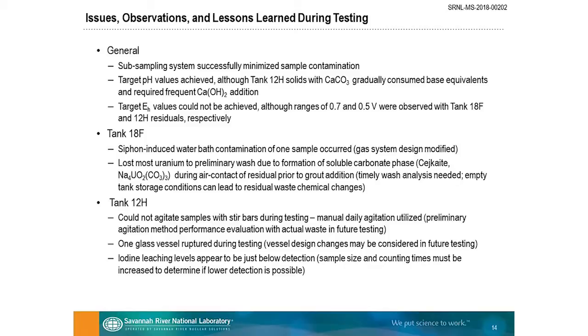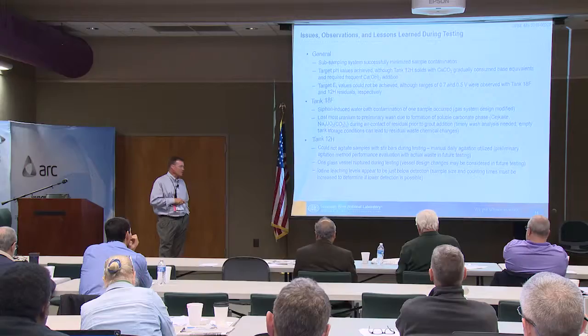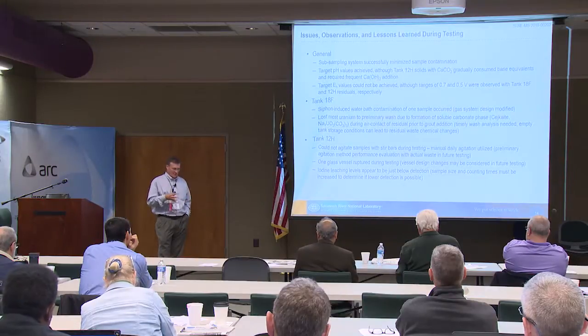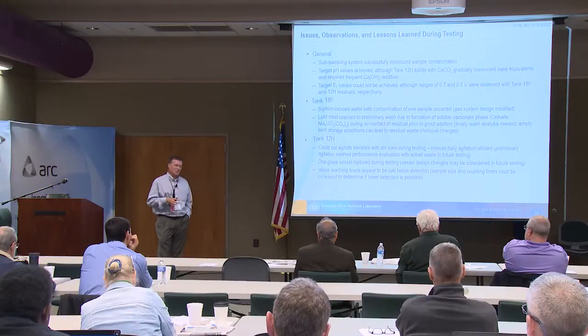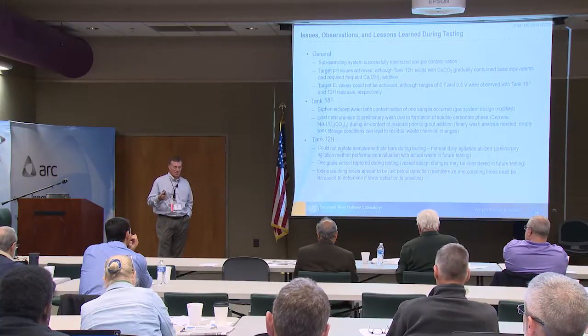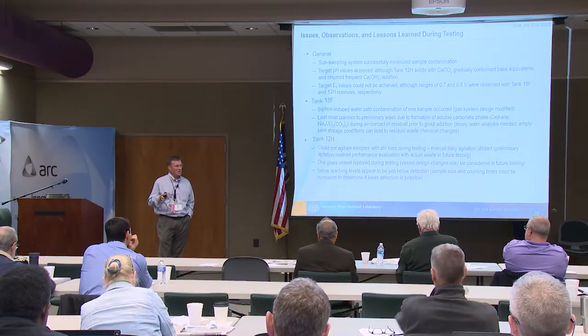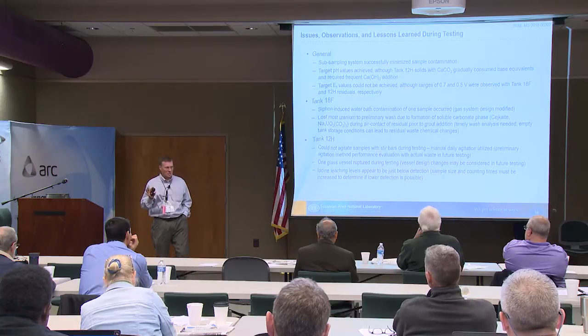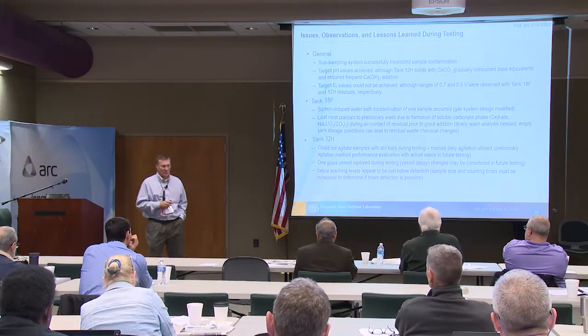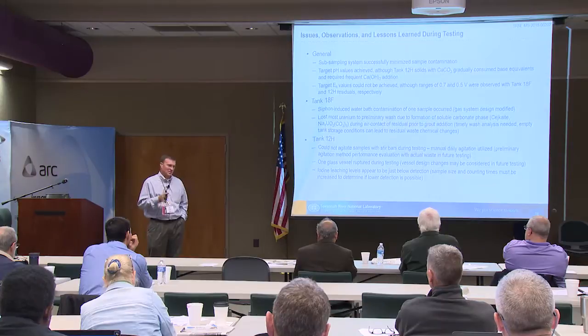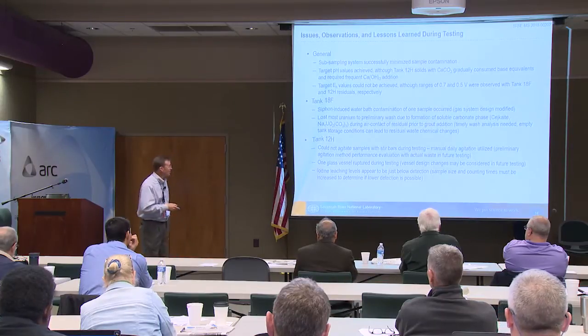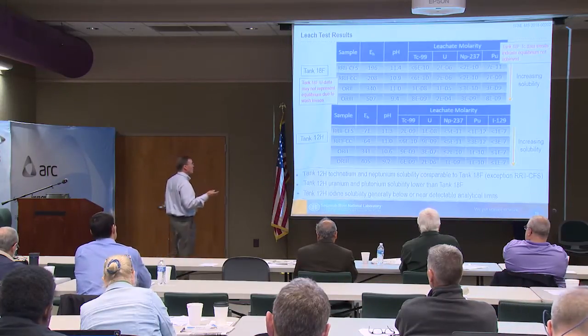Iodine leaching levels for tank 12 were right at detection or just below. And the more sample volume you can give them, the longer counting times they use, the lower detection they can go. But we were pretty low, down in single-digit DPM per mil. But in the future, we may try to design the test a little differently to get them more volume.